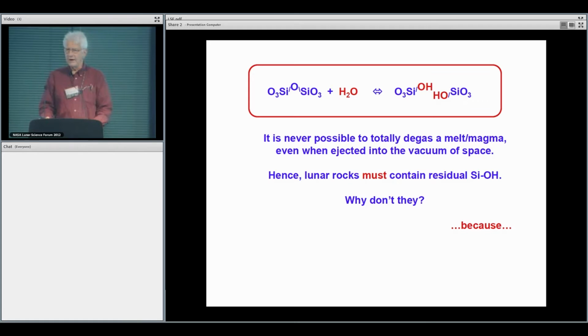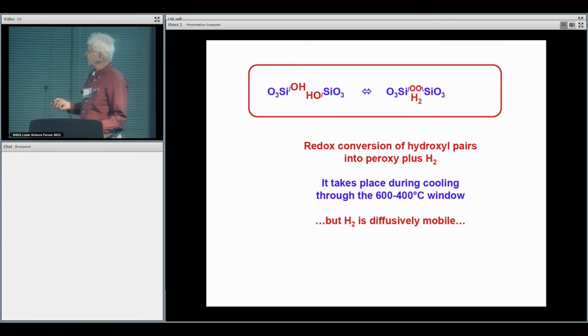But then the question arises, why is the amount of residual OH in much of the lunar rocks so small? Well, there is one reaction, in the next slide, which we discovered some time ago, where you have the hydroxyl pair, that during cooling, and we know more or less the temperature interval in which this happens, between an upper limit of about 600 degrees and a lower limit of about 400 degrees, there is a redox reaction. Electrons are being donated by the oxygen to the proton. Both protons get together, form molecular hydrogen, and the oxygen becomes oxidized to the peroxy state, from the formal valence state 2- to the valence state 1-, forming a peroxy bond.